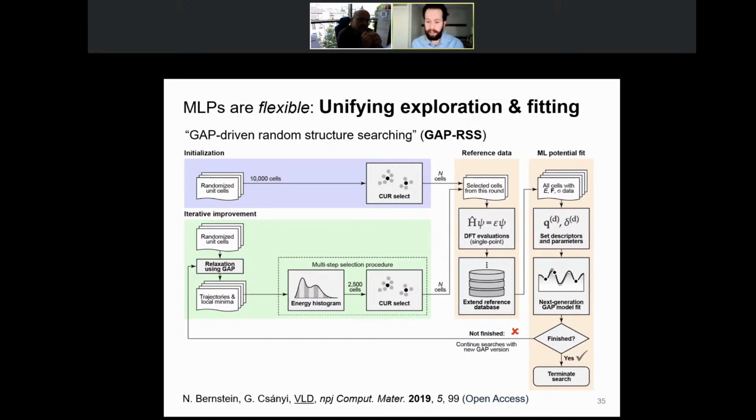In that paper that I'm showing here, we've searched with unit cells up to 24 atoms per cell. So of course that means if you'd be looking for a structure which is, as you say, very, very weird, you might not be able to find it immediately. You might want to tune the parameters if you know you're searching for something which is very, very strange.